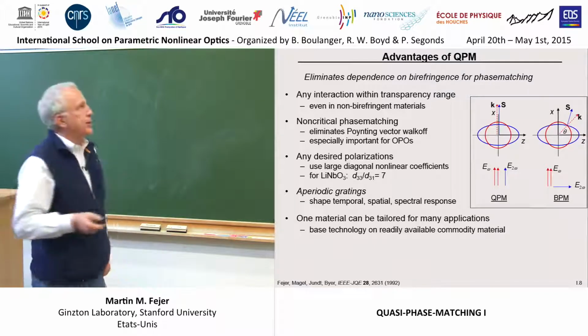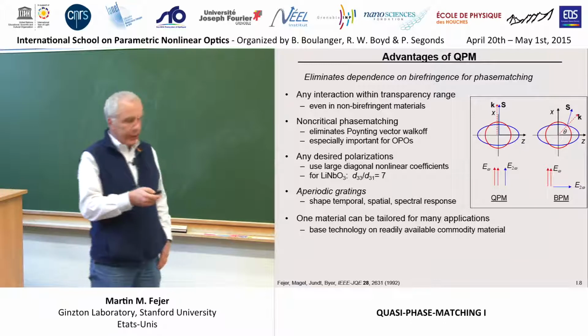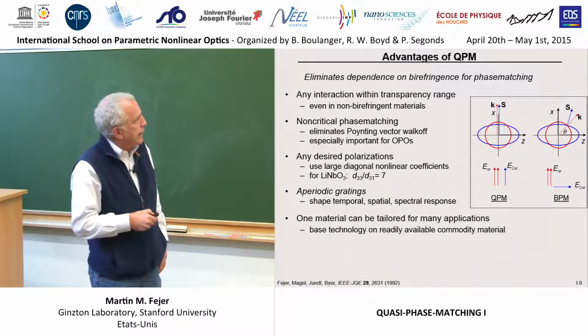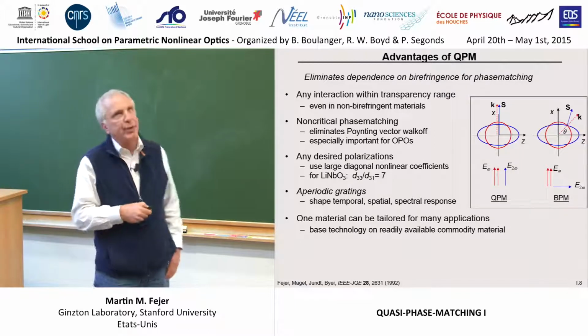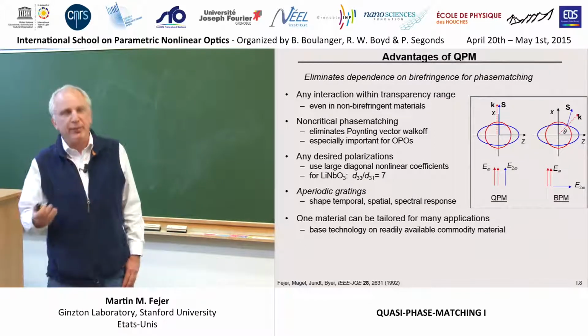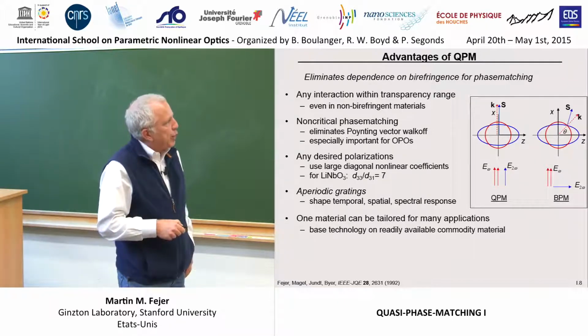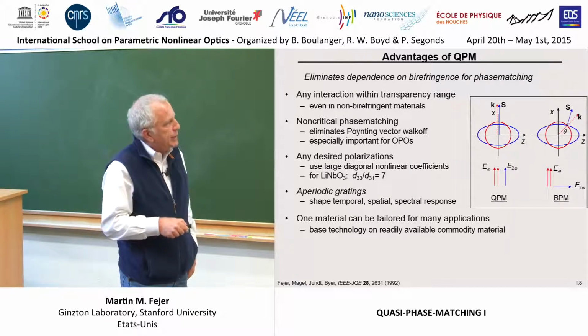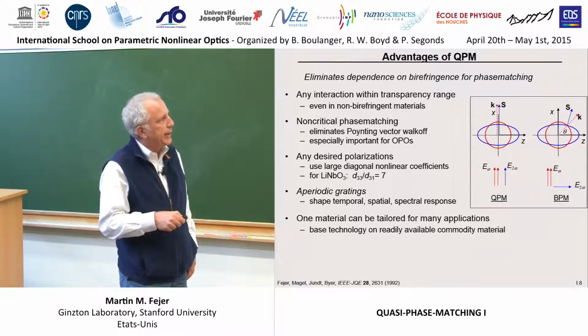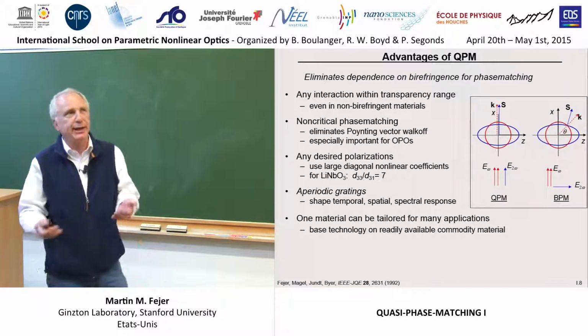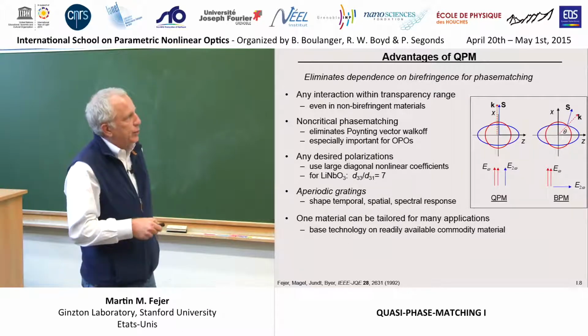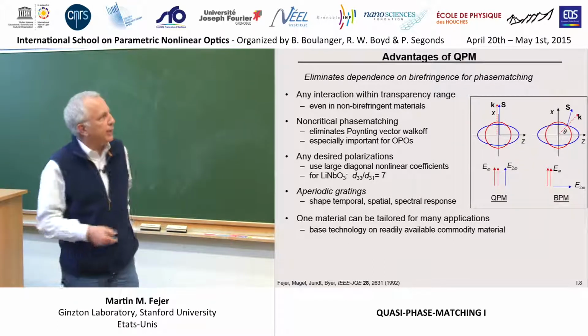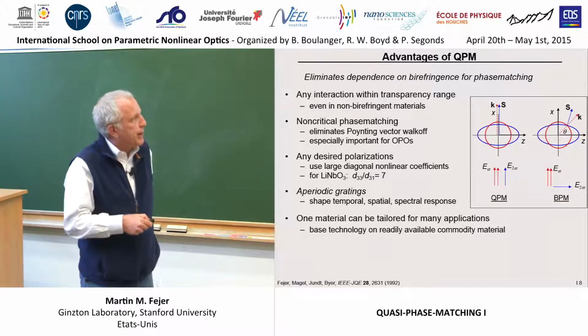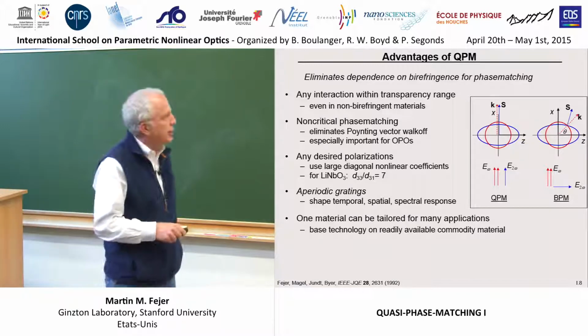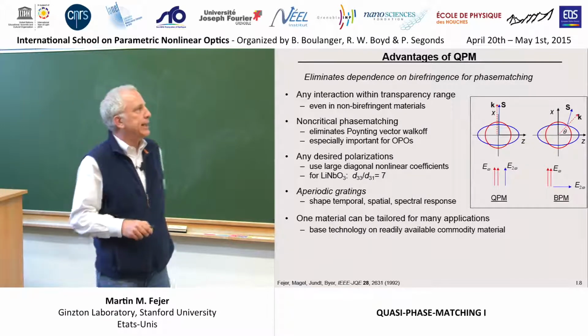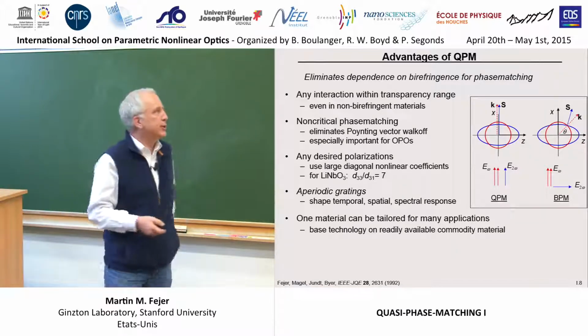So what are the advantages of quasi-phase matching over conventional phase matching? Again, we've heard several of these already discussed. One key one is that you can use any desired combination of polarizations for the interacting waves that are convenient for your purposes. One particularly important point is that since you aren't relying on birefringence to overcome the dispersion, and that then determining a particular combination of polarizations and propagation directions, often leading to critical phase matching and Poynting vector walk-off. In a quasi-phase match crystal, you're relying on this periodic structure to accomplish the phase matching, so you can always propagate along an optical axis, which means you always have non-critically phase-matched interactions, at least if you want them.